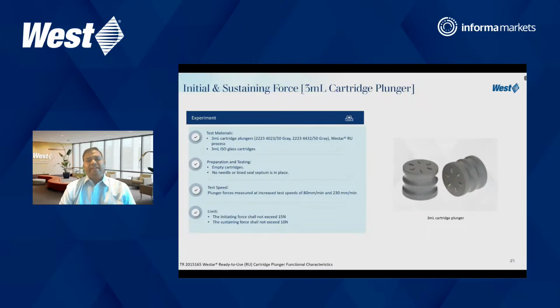Again, moving to the data with the 3 ml cartridge plunger, which most of the GLP-1s use. We have both chlorobutyl and bromobutyl options. The design for this 3 ml is 2223. 4023 is bromobutyl, while 4432 is the chlorobutyl option. Here also we have generated data, but we tweaked the testing speed. As per the ISO, the speed mentioned is around 50 millimeter per minute. But just to understand what the initiating and sustaining force will be for this 3 ml cartridge plunger with increased test speed, the speed was increased from 50 to 80 millimeter and a maximum of 230 millimeter per minute.